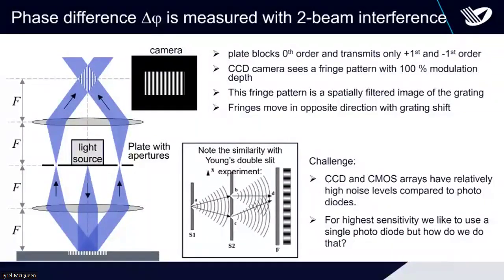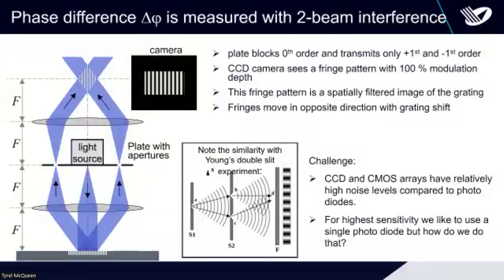How does that work in a sensor? You basically take a light source, you diffract it from the grating. The zeroth order is getting blocked out, so it's called a dark field measurement technique. And then it's getting refocused on the detector. Then the crossing of these two forms an image of the grating. So that's what the image on a camera would look like. Basically, you just see a fringe pattern with 100% modulation depth. The challenge here is you don't really want to use a camera that's slow, and it has a comparatively high noise level compared to a photodiode, which also is cheap. So we like to use the photodiode.